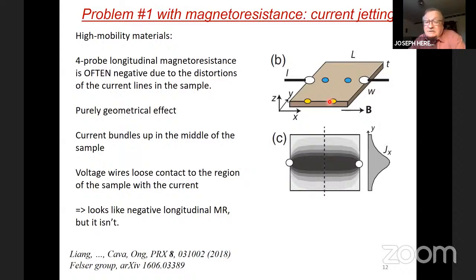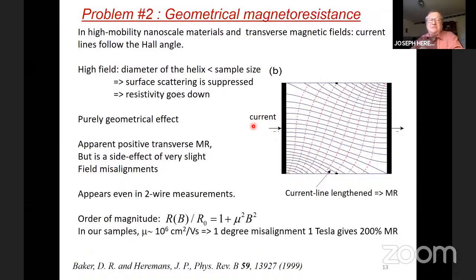It isn't. It's not a magnetoresistivity, it's just a magnetoresistance, but it's a macroscopic effect due to the distortions of the current lines. That is called current jetting, and it's been treated at length by several of our coworkers, by several colleagues, including here. We know how to avoid this. We have to make long thin samples and put the electrodes on the top. It was a lesson that took a few years to learn, but we know how to do it.